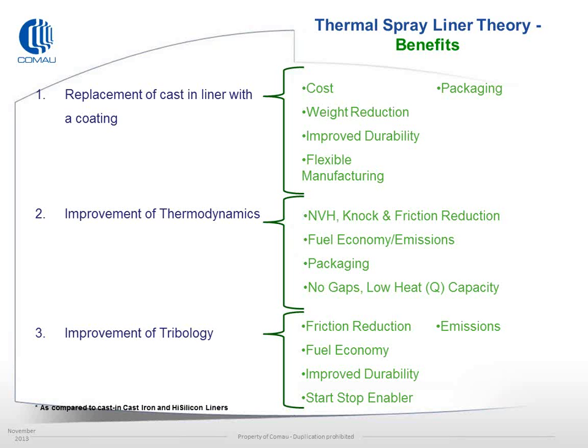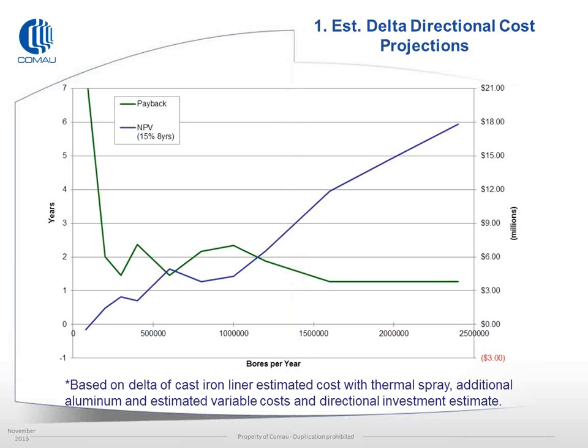Improvement in tribology, because we are going to a harder phase material. Typically it's a mixture of oxides as well as martensite and bainite. Produces a fairly robust wear surface. On top of that, the intrinsic porosity within the process allows us to contain and create pockets of oil on the surface, which really literally help slide the Stribeck curve to the left, putting us directly into hydrodynamic immediately versus having a lot of mixed mode. Benefits for that go on and on, anything from start-stop to reduced friction, of course.